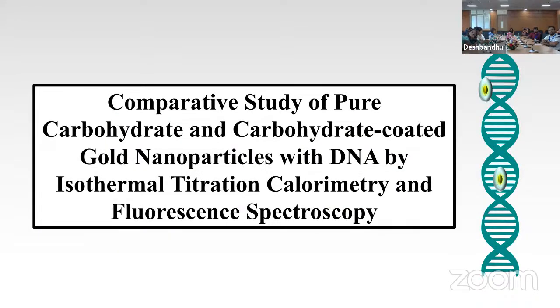Now, the detailed comparison of the interaction of thermodynamic parameters, pure carbohydrate and carbohydrate coated gold nanoparticle, to know the effect of coating on the surface of the nanoparticle. This was done by isothermal titration calorimetry and fluorescence spectroscopy. For the ITC experiment, DNA was taken in the cell of the ITC and the syringe was filled with pure carbohydrate or carbohydrate coated gold nanoparticle to achieve saturation at the end of titration.